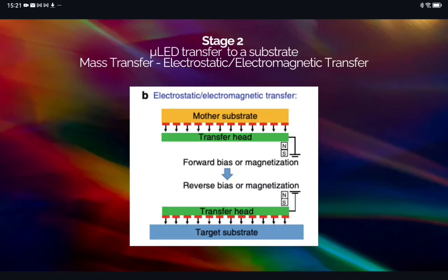The second method is electrostatic transfer techniques. These techniques utilize voltage-induced adhesion to transfer micro-LEDs. First, the transfer head sticks to the micro-devices by applying a positive voltage to the electrode in the transfer head, creating a grip force on the micro-device to lift off the devices from the mother substrate. Then the micro-LED on the transfer head will be released onto the receiving substrate by applying a negative voltage to the other electrode of the transfer head. This technique enables large-scale micro-LED transfer, but it may cause LED breakdown due to application of high voltage.